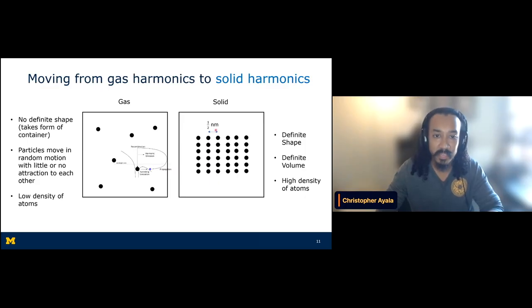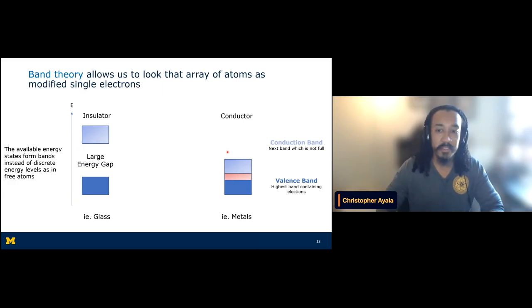Whereas now within solids, the typical spacing tends to be about 0.5 nanometer, and there's a definite higher density of atoms. So now you have to take into account how these atoms and harmonics interact with other atoms around it. And to do so, we will use something called band theory. Band theory allows us to look at this whole array of atoms as just modified single electrons. So instead of these discrete energy levels that we know and love in the free atom, we now have what's called energy bands.